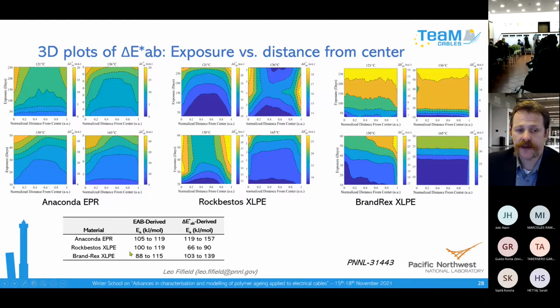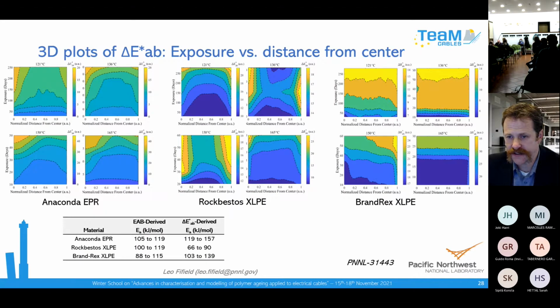So for these three examples, we compared activation energy derived from the EAB versus derived from the color change, and we saw some differences. These are just one data point, limited to what we looked at. But in this example, we saw a decrease in the activation energy compared to what you would expect from the EAB. So that might be a point of concern that maybe the cable is not going to last as long as you think it is if you're using a technique that doesn't account for these artifacts that happen during accelerated aging. Any questions on that in the homogeneous aging part?